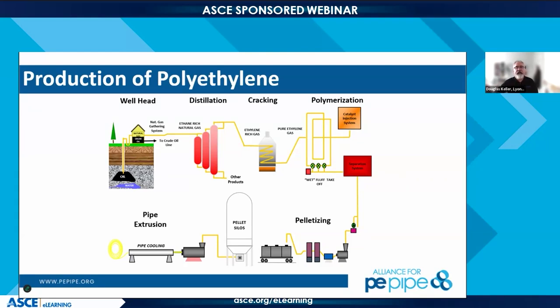In the pelletizing step, we add the additive package that is needed for the particular application, and we produce pellets. If you've ever had a Beanie Baby explode on you, those are those little pellets that are inside. They're about the size of a BB, maybe 4 millimeters in diameter, sometimes cylindrical, sometimes spherical. We load those materials into a rail car. The majority of polyethylene is shipped to our customers in rail cars. Rail transport is an extremely efficient way to move polymer around the country. When it gets to our customer, they unload, check the material and make sure that what they received is what we should be sending them, load it into their pellet silos, and then they go through the pipe extrusion step. Now, Alan, if you can go to the next slide.